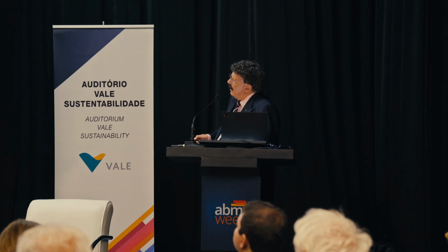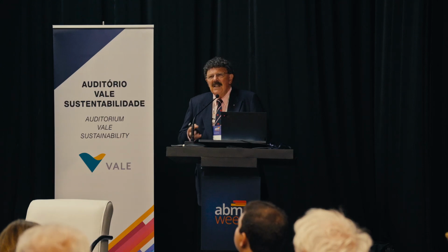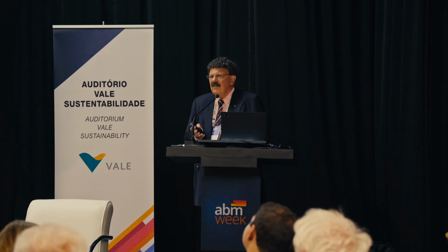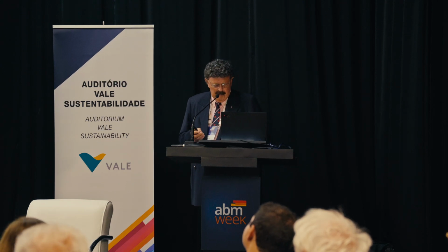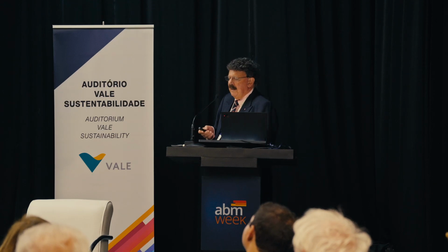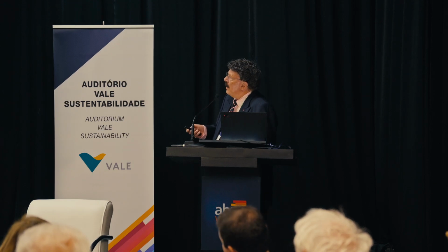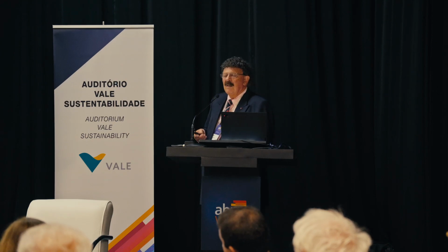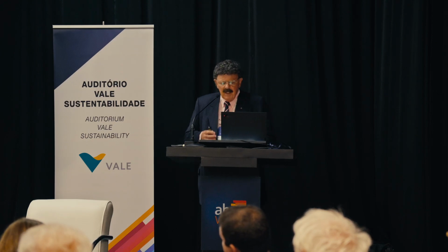They're a little different because we have these honeycomb structures with high dislocation densities. They're just a variant of what I talked about before, but they do operate in a slightly different way because of additive manufacturing. This is one of these banana curves of toughness versus, I think that's ductility or yield strength. And you can see we get properties that are a little bit better up here with that technique.